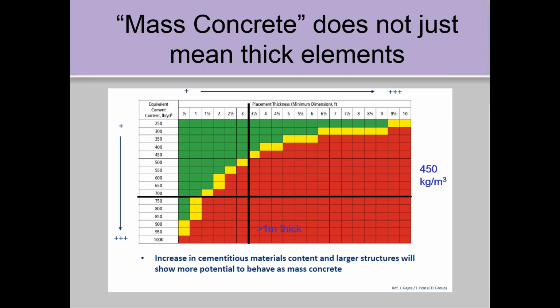And this is an interesting graph. It's from a paper in one of the ACI special publications. Unfortunately, it's in US units, but I like it because it shows where you've got a concern. So the vertical bar shows anything greater than 1 meter to the right, less than a meter to the left. And that horizontal bar is 450 kgs of cementitious materials, and so higher at the lower end. So even when you have lower cementitious materials contents and less than a meter thick section, these red zones are severe areas of high risk of thermal cracking.